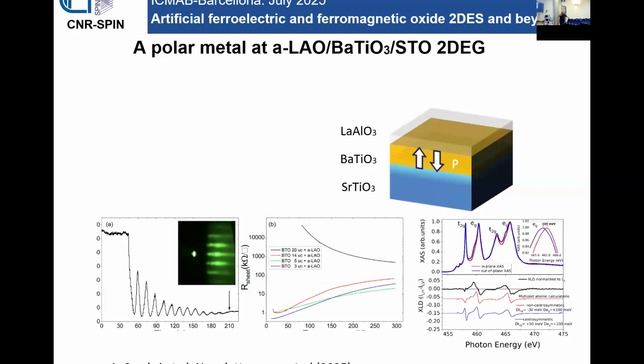We know that it's polar because we see the XLD signal, and we also see a second harmonic generation signal. So for sure it's polar, but whether it is ferroelectric, in the sense that you can switch it, at the moment we are not sure. I don't know why KNN seems more robust from the point of view of ferroelectricity. That's our experience with barium titanate. Another thing is that in barium titanate the 2DEG forms inside the barium titanate, while in KNN the 2DEG should not be present.